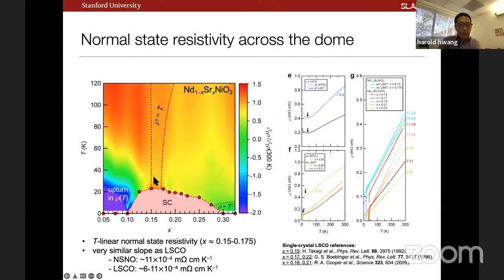Now, to give you a qualitative first look at the underdoped and overdoped regimes. Looking first at the underdoped regime, I make this comparison again to changes in the crystallinity by moving between substrates. The resistivity was originally higher. The scale of the resistivity has come down, but the qualitative features, namely this resistivity upturn, are fairly robust. So that's still something that we observe. And I'll say more about that in a slide or two.